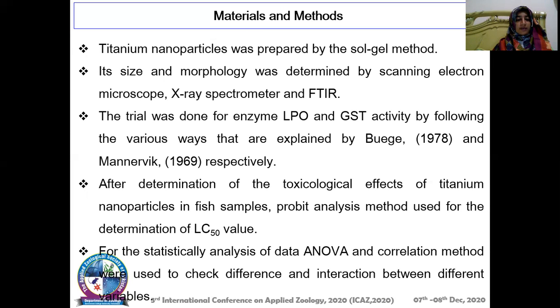And when all the fishes had died after the 4 day trial, I checked the physico-chemical parameters on a daily basis according to toxicity trials. The mean 96-hour LC50 of titanium nanoparticles for Cyprinus carpio was calculated as 168.58, while the lethal concentration was calculated as 289.249 respectively. These values were given by the probit analysis method.